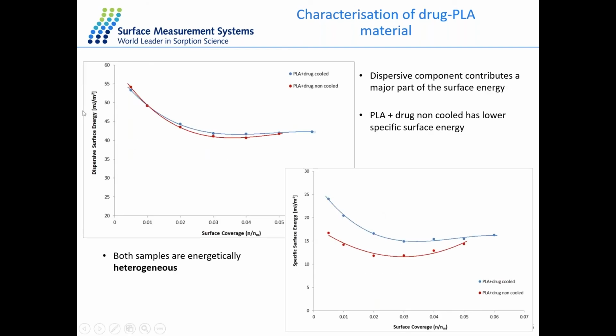So what we have here is the dispersive surface energy with increasing surface coverage of our cooled and non-cooled samples. What we can see first is that we have quite a curved profile. So this is telling us that our sample is quite heterogeneous. We can also see how similar these two are. So in terms of heterogeneity and dispersive surface energy, these two samples are quite similar.